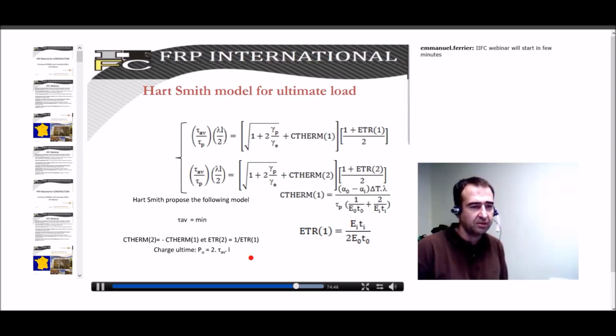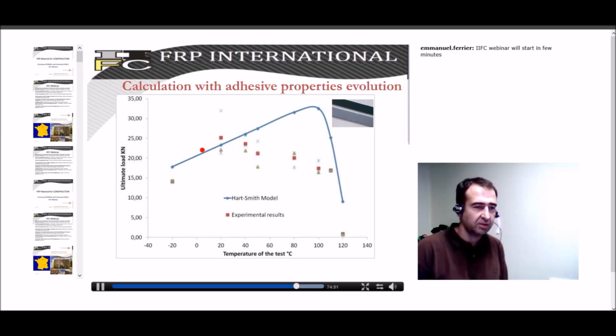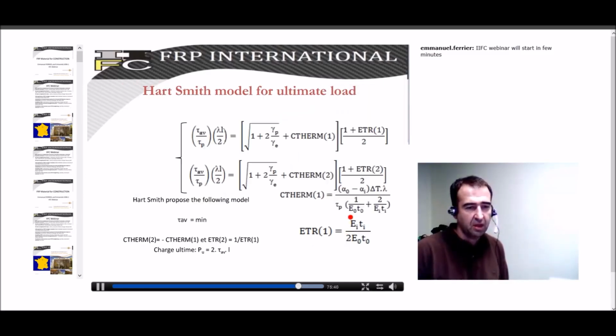Depending on those calibrated values, if we use his model and try to identify the ultimate load based on our results, we can observe that this model doesn't work. It means that when the temperature increases, the ultimate load should be much higher than the one we observe in his model, and if we compare to the obtained results, it's very different. In fact, the problem is that Hart Smith works on thermoset polymer, and the temperature was much farther from the glass transition temperature. It means that all his model has been calibrated on the glassy plateau, so it cannot be used in our conditions, because in this term you have here the Young modulus of the epoxy polymer, and this value is not constant because it depends on the temperature.